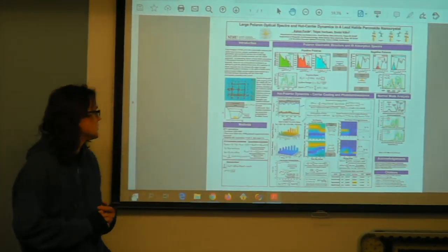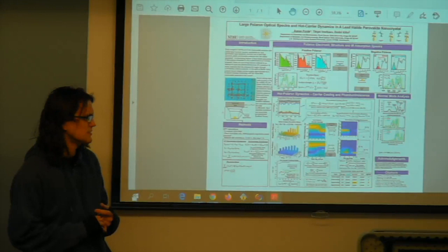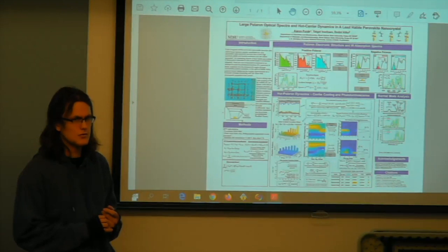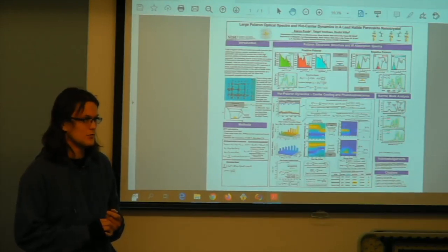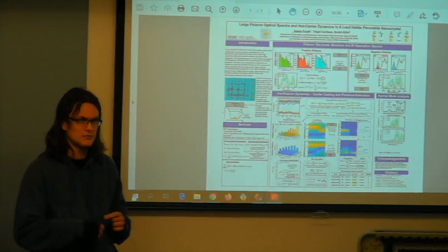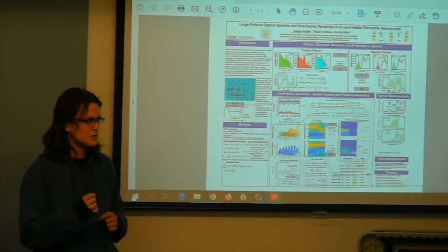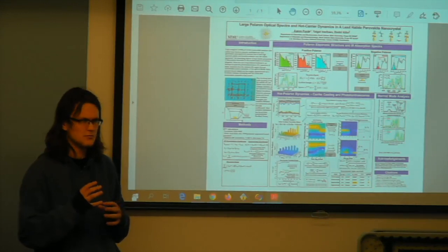And then for the dynamics, I hit a snag because the models generally don't seem to be very stable, or it's hard to get VASP to converge on them. Essentially, if I try to run the model for long enough, the ligands desorb from the surface and it just starts to break apart.